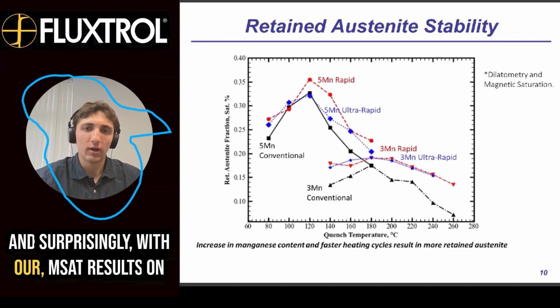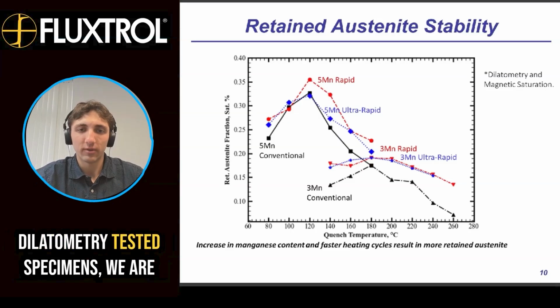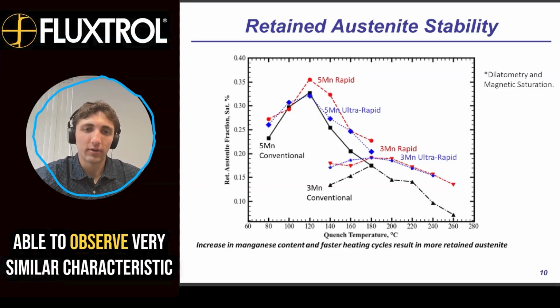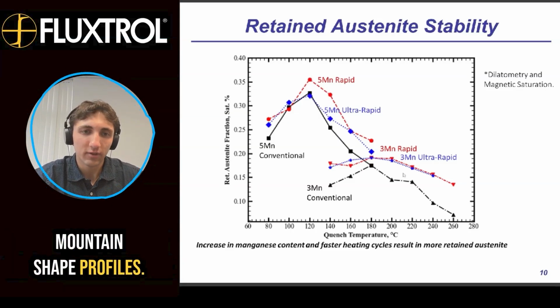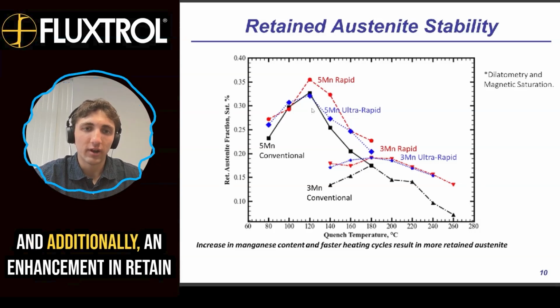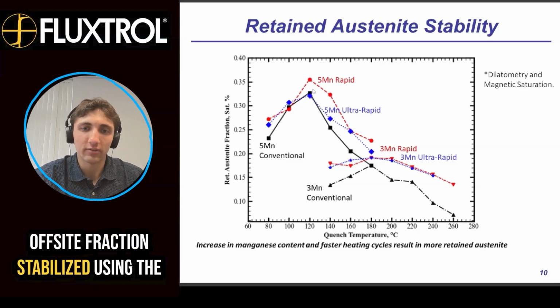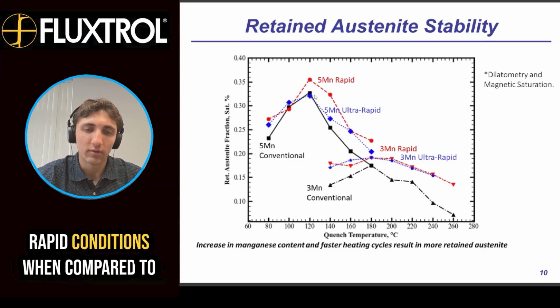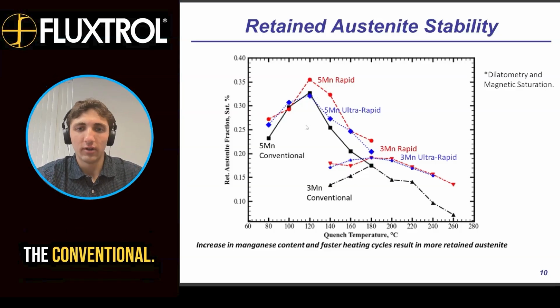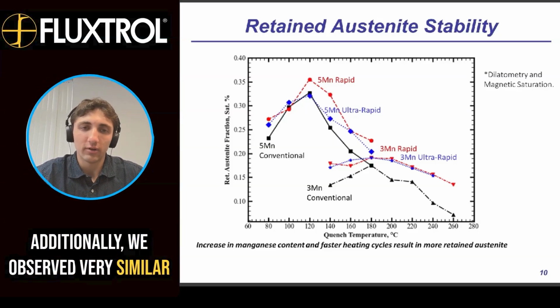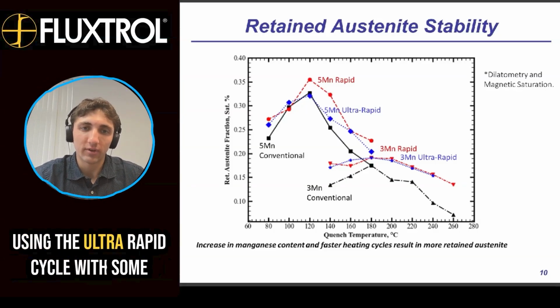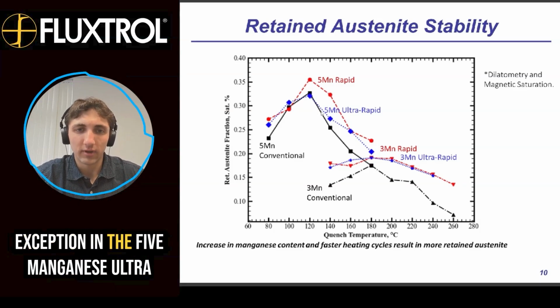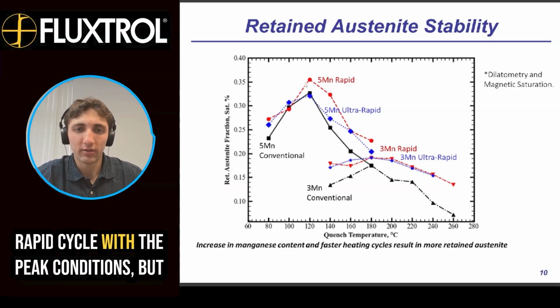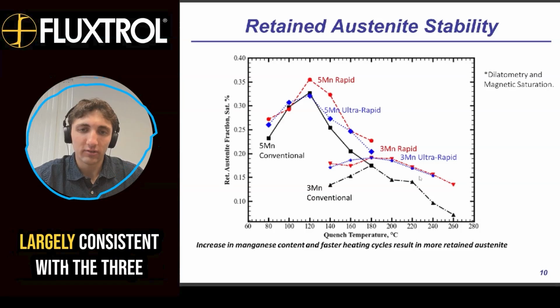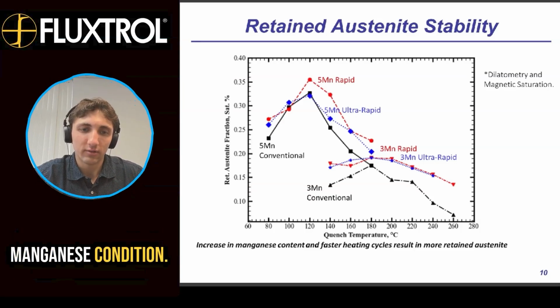And surprisingly, with our MSAT results on dilatometry tested specimens, we were able to observe very similar characteristic mountain shape profiles, and additionally an enhancement in the retained austenite fraction stabilized using the rapid conditions when compared to the conventional. Additionally, we observed very similar retained austenite fraction stabilized using the ultra rapid cycle, with some exception in the 5 manganese ultra rapid cycle with the peak conditions, but largely consistent with the 3 manganese condition.